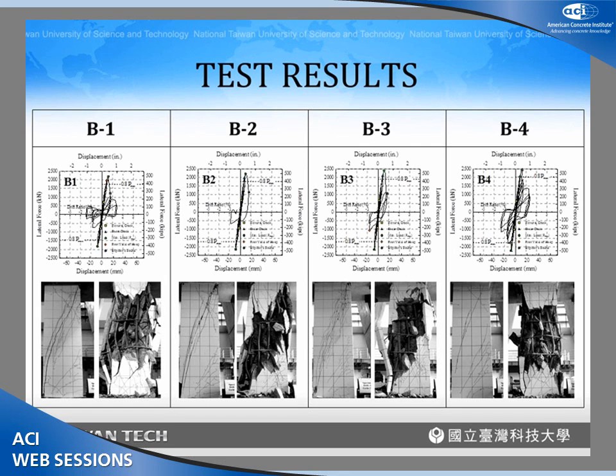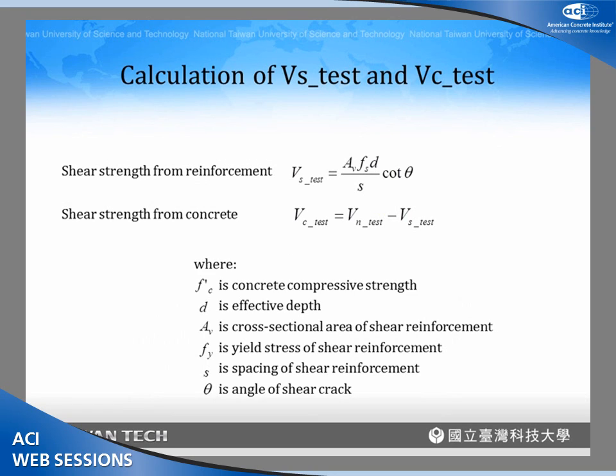From the test result, we are able to measure the shear strength, but this is the total shear strength. And when we design the shear strength of a column using the ACI code, we know that there are two parts of the shear strength. One is the shear strength from the reinforcement. The other one is the shear strength from the concrete. And we don't just look at the total shear strength. We want to decompose the shear strength from the test result into two parts. One is from concrete, the other one is from reinforcement.